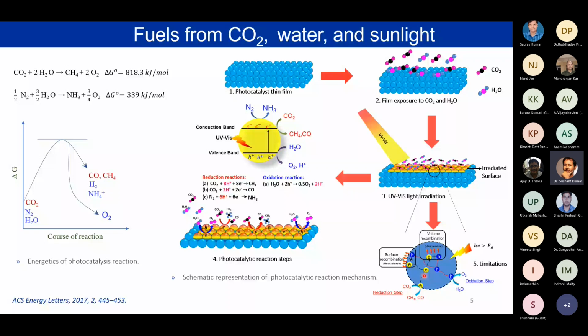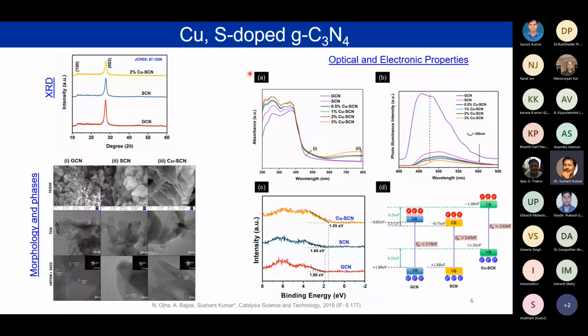Now, the first work here is about copper and sulfur doped in graphitic carbon nitride. Graphitic carbon nitride is a 2D material which has a very nice band gap, 2.7 eV, which falls within the visible light range. So that satisfies one of the criteria that we have. Now, using the synthesis method, we doped the sulfur by calcination of thiourea, and graphitic carbon nitride is prepared by calcining melamine at 500 degrees Celsius for 4 hours. And then we doped the copper in the photocatalyst that we prepared.